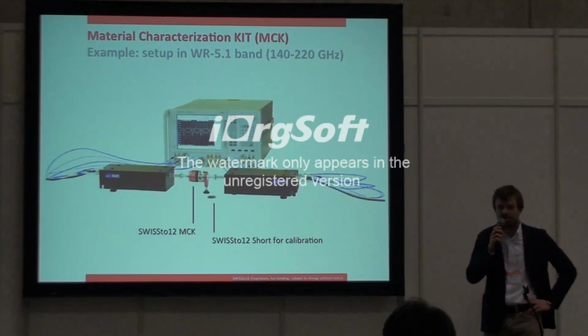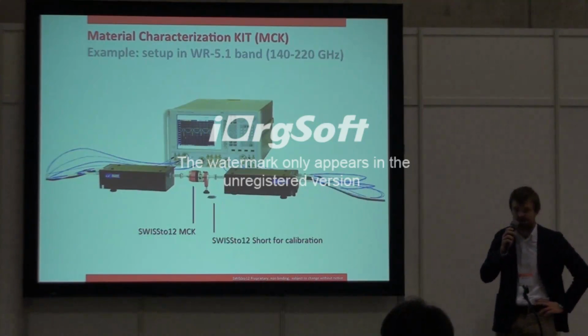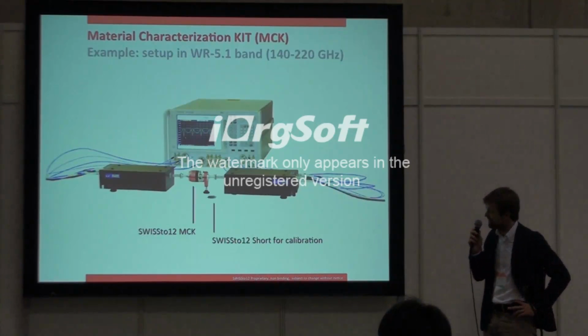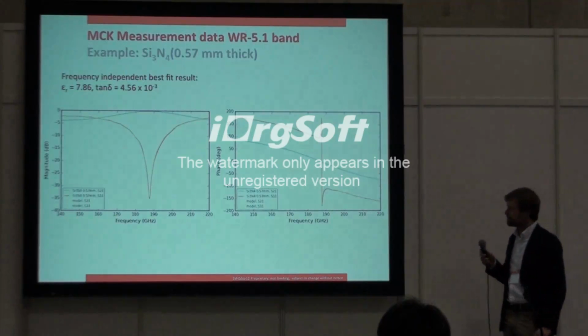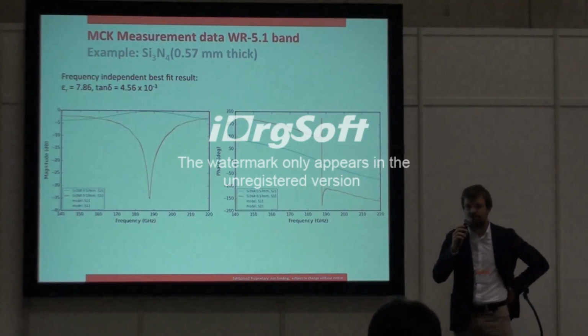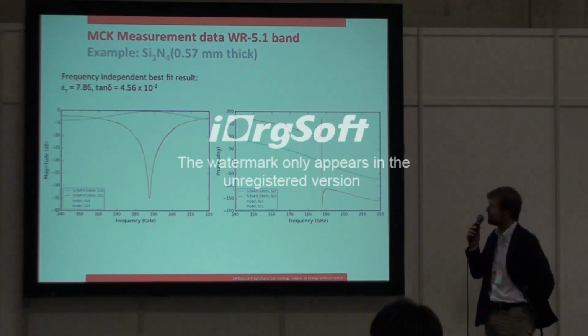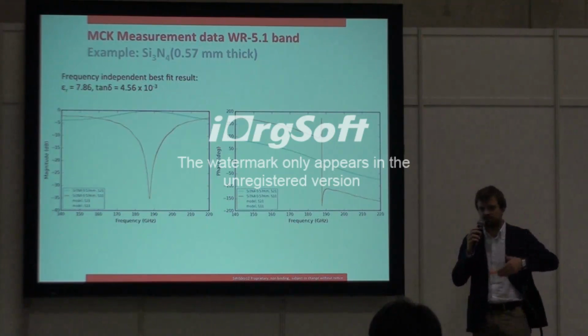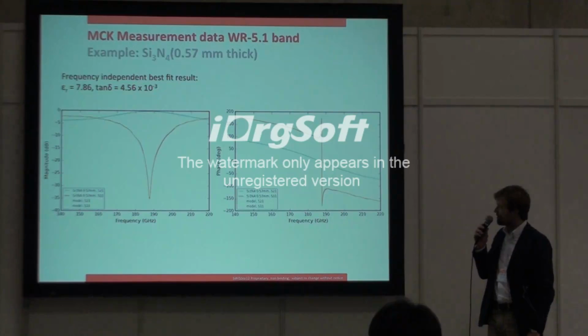A second example of a system, this is a system at a lower frequency band, the WR5.1 band, so between 140 and 220 gigahertz. Again, same system architecture, a VNA with frequency extension modules and an MCK. At this frequency, we again have materials that have a constant behavior in terms of frequency dependence of permittivity. So here we have silicon nitride, Si3N4, about 0.5 millimeter thick, where we are able to resolve again the strong resonance features that we see inside those materials, and where the constant epsilon model gives good agreement with the measurement.